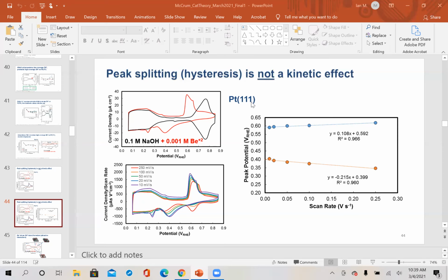I've also done some work with some of the PhD students in Mark's group looking at the formation of surface oxides of platinum. And we see that above a certain critical oxygen coverage, it's favorable to start making locally very high platinum oxygen coverage structures. So you actually lift platinum out of the surface and make a very high local coverage of oxygen, which is kind of like an islanding of the oxygen on the surface. And so it could be that that's related.